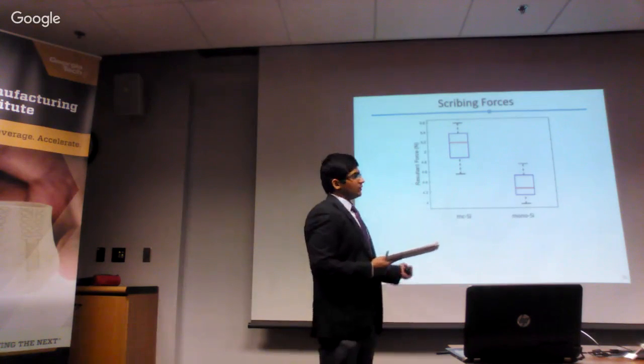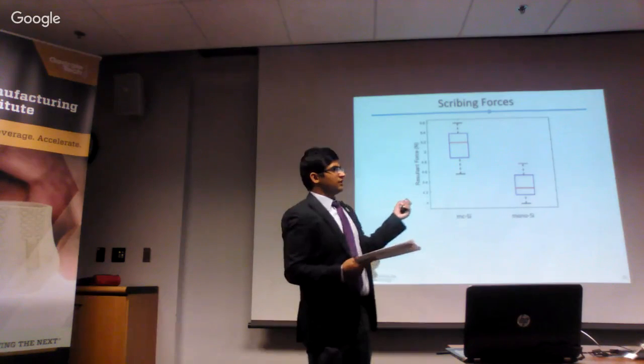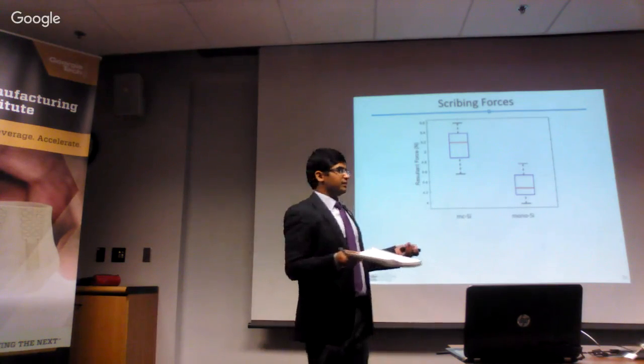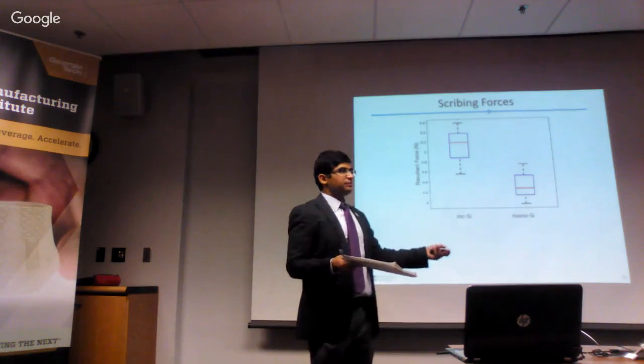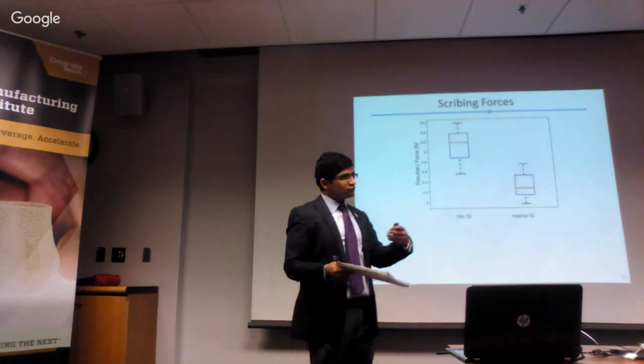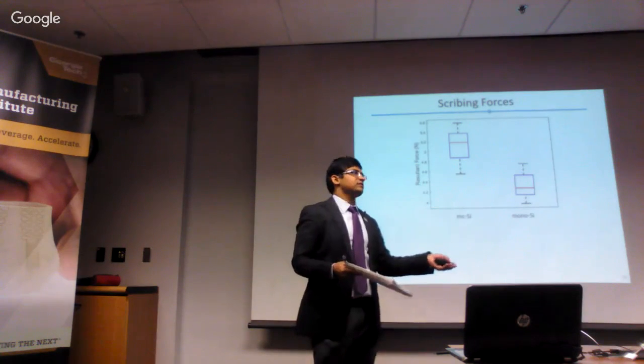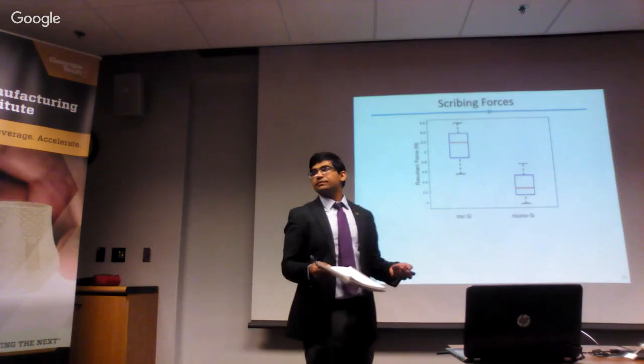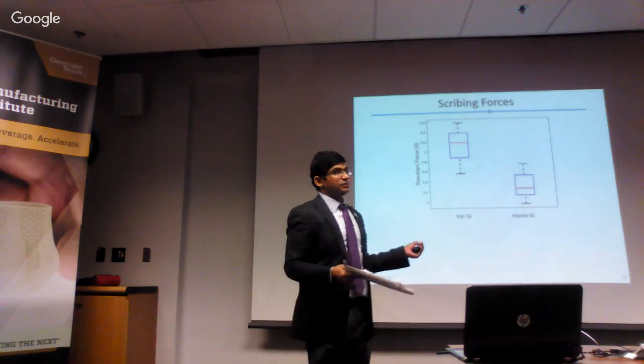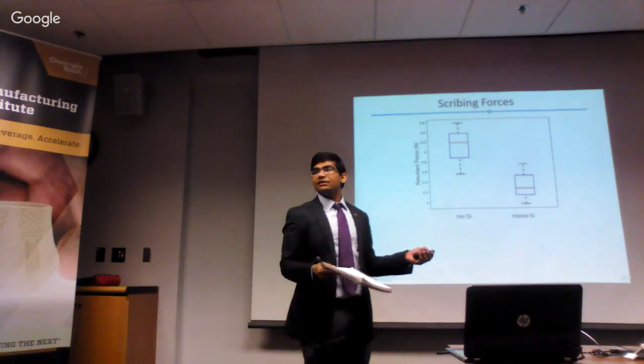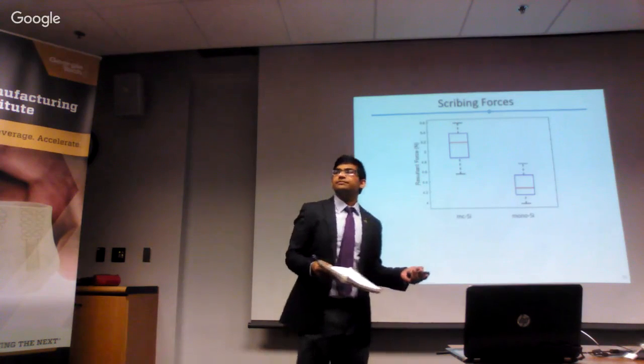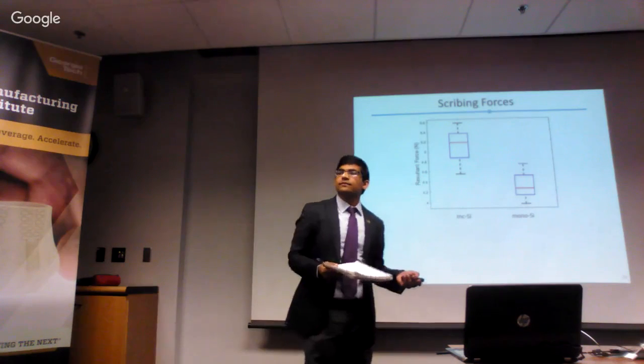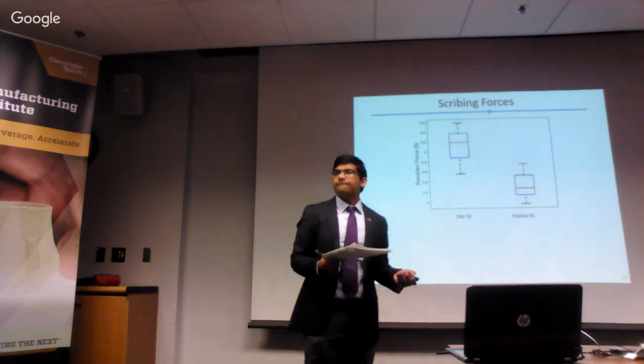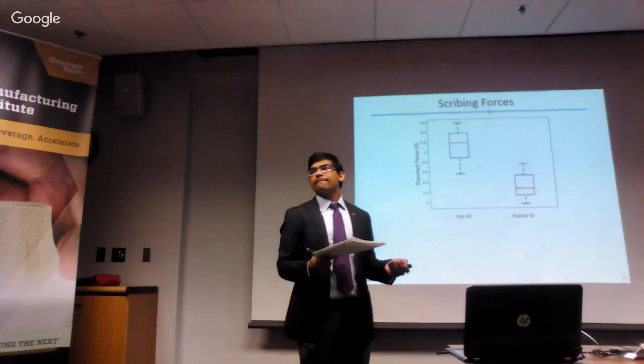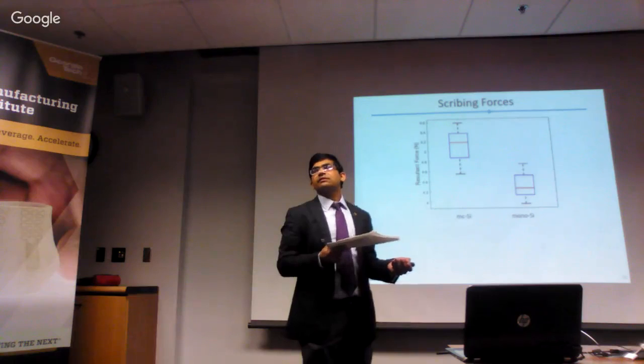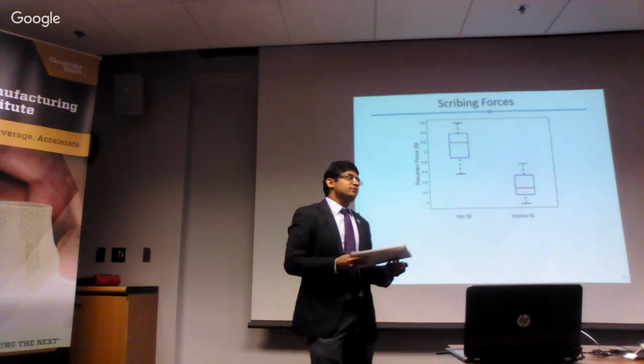So the result you showed was representative. I think the thesis and the papers had more results showing other grain shapes driving across the grain boundary, and a distinct difference in the cracking frequency across the boundary. But the question Dr. Saldana is asking is, in this experiment, going 20 millimeters, multi versus mono, did you see a noticeable effect of the different grains and discontinuities you encounter, either in the cracking frequency, morphology, surface characteristics, or in the forces? That's really what he's asking.